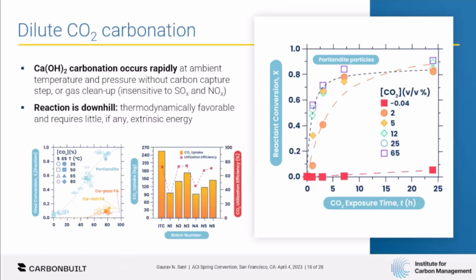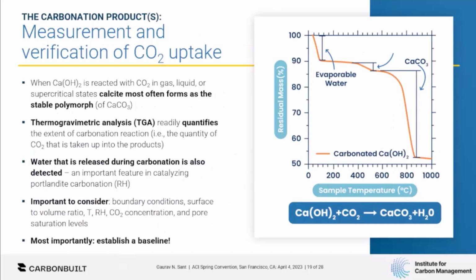As an example, on a carbonating surface, calcium hydroxide actually carbonates to completion. You get an exchange reaction of hydroxyl for carbonate. You produce water on the surface, the water auto-catalyzes the reaction, and you're able to take the reaction to completion in a matter of hours, right? So in 24 hours, you can essentially take the reaction to completion. We were focused on 24-hour periods. Why? When you think about precast masonry, we were thinking about how long it typically takes to go through a process of the sort. And 24 hours turns into a really nice number to be working with.